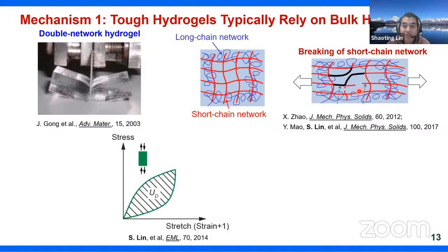Okay, that is essentially the key mechanism for this large hysteresis loop as manifested in this nominal stress versus stretch curve. Okay, so let's think about it. What happened during this loading and unloading process? When the material is deformed, both the short chain and long chain networks bear the mechanical load. However, once the material is unloaded, since the majority of the short chain network is broken, they lose their load bearing ability, therefore giving a much reduced stress level. We denote the enclosed area of this loop as UD, which is the dissipated energy per unit volume of the material. We further denote the enclosed area of the loading curve as U, which is the stored energy density of the material, and the ratio between UD and U defines the hysteresis ratio of the material.